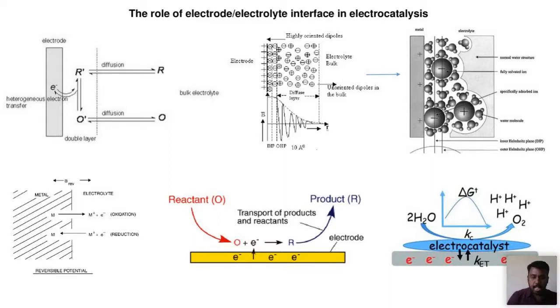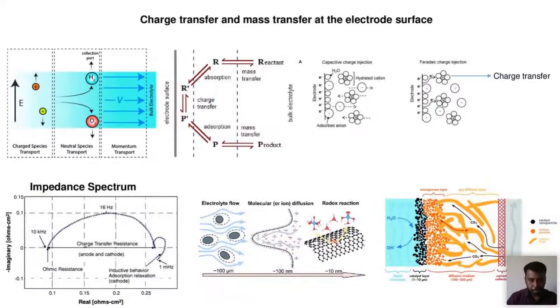Oxidation and reduction reactions can happen at the electrode surface depending on the electron transfer. When the electron is accepted, a reduction process will happen. When the electron is released from the electrode, then an oxidation process will happen. So the reactant and product will be generated on the electrode surface with the adsorption of the reactant and the release of the product. We have to consider the free energy for each adsorption of the intermediate. This you can obtain from DFT calculation. This information will be very useful for determining the mechanism.